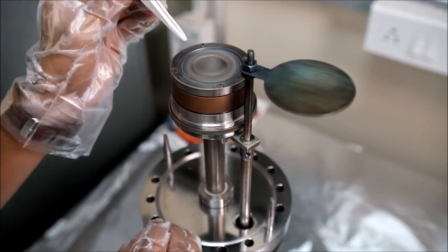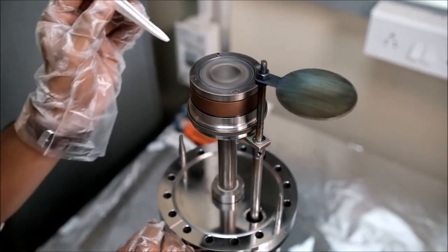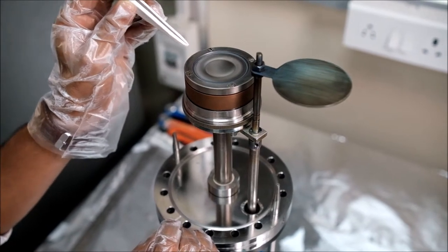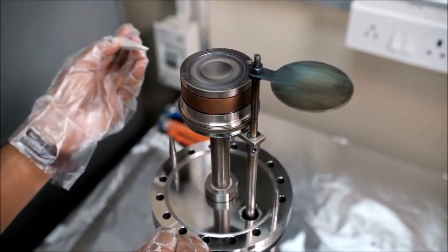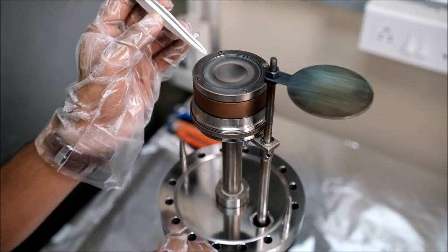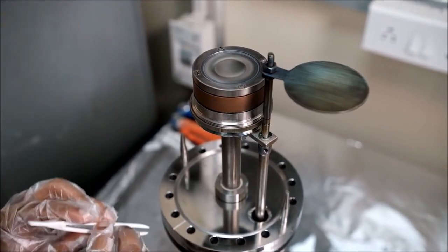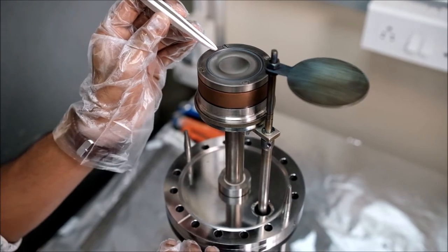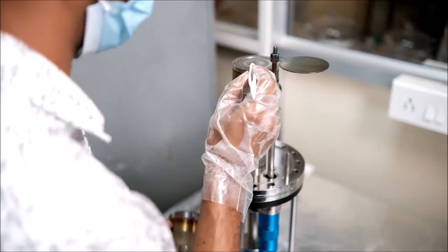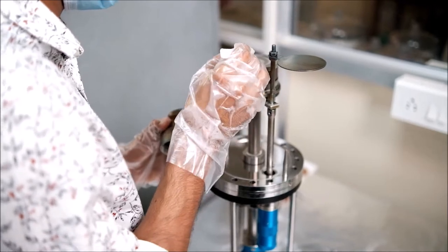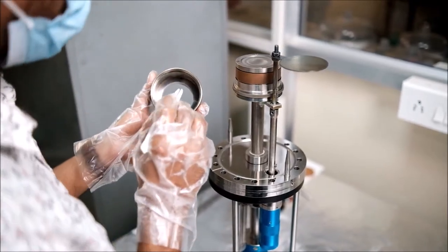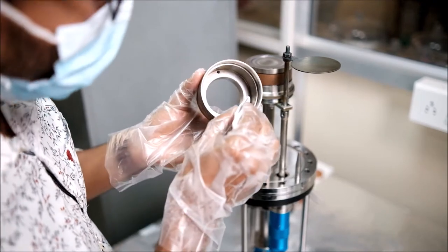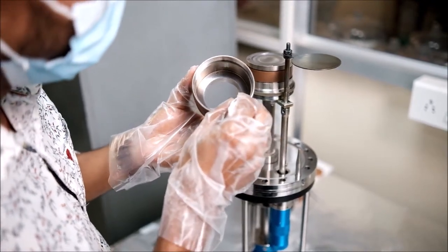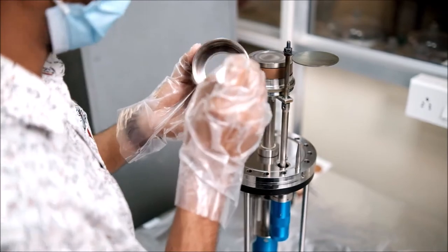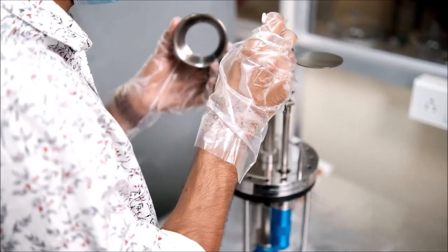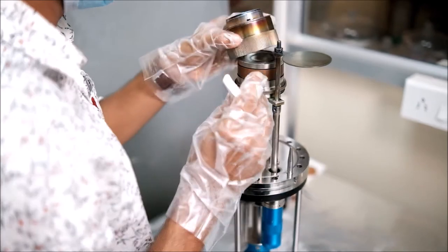This is important because as we hold the gasket and the target, all the parts are connected to the power source. So if we keep it open, then sputtering can happen from all over the surface area. But we don't want to sputter this steel material. So to cover this steel material and also to specifically sputter out the target material, we'll attach this. So you see in the holder, this structure hinders the argon ions from sputtering out material from this gasket material.